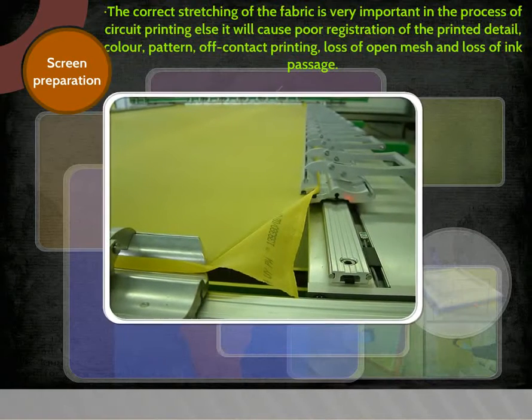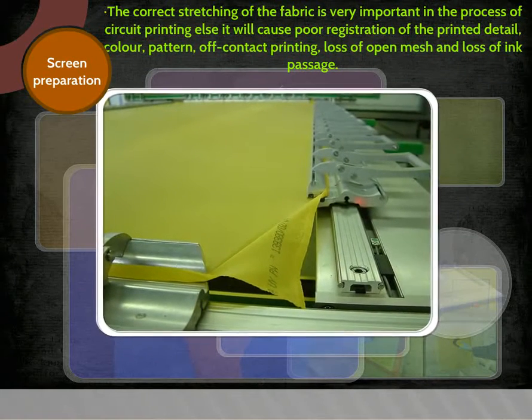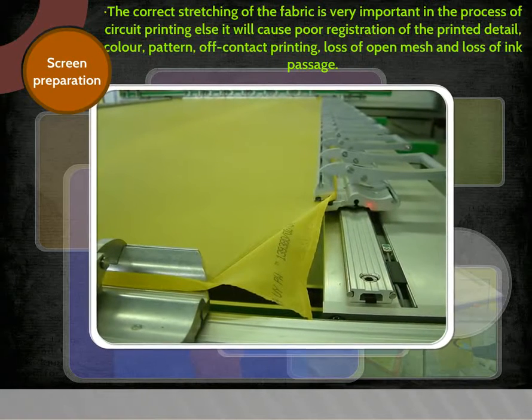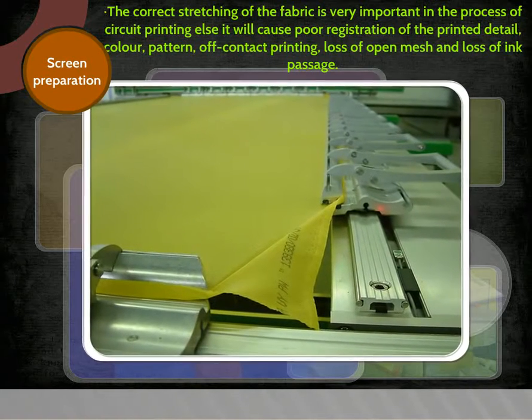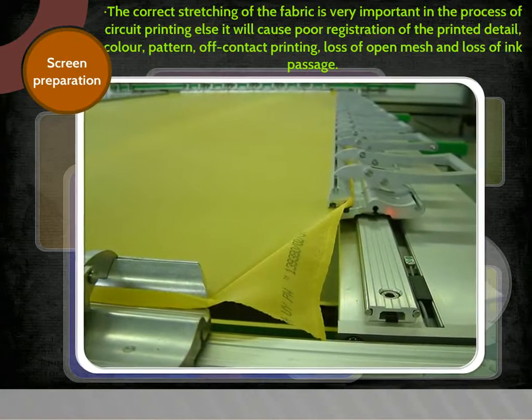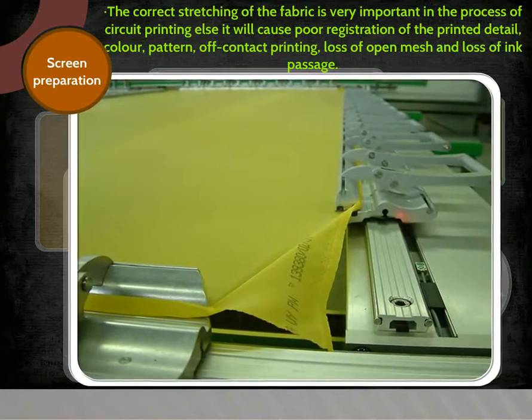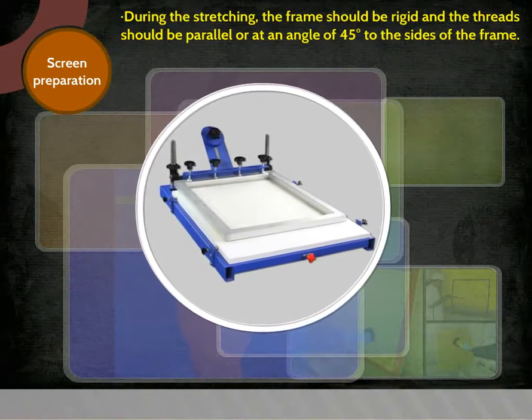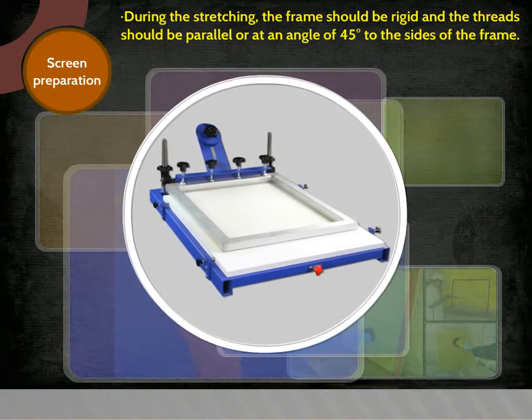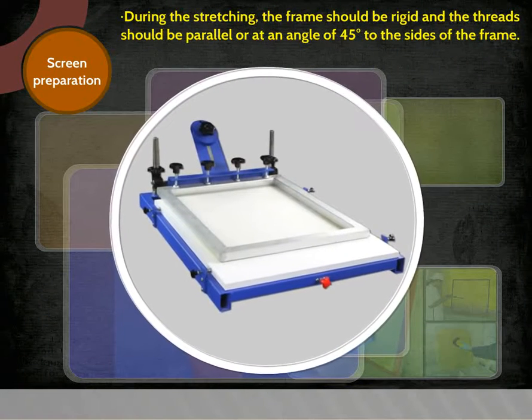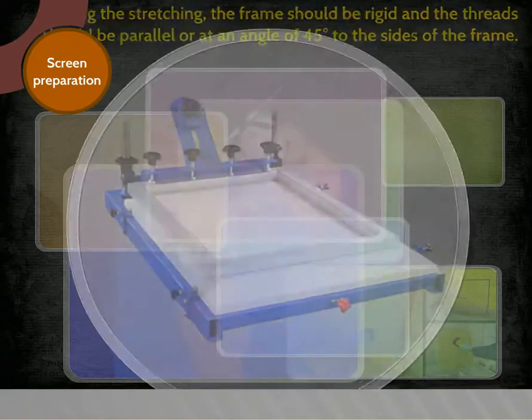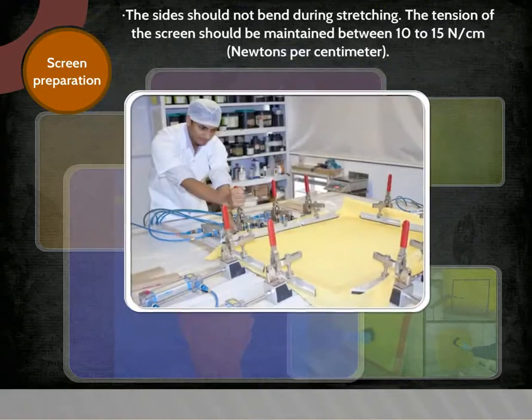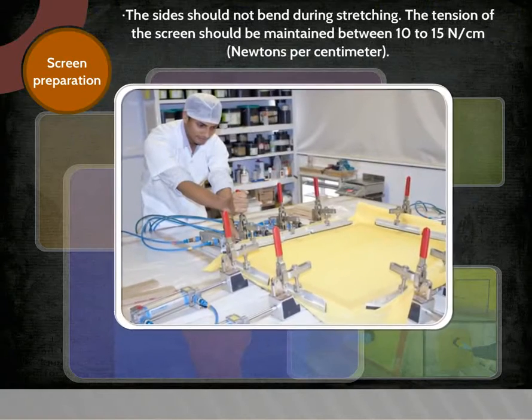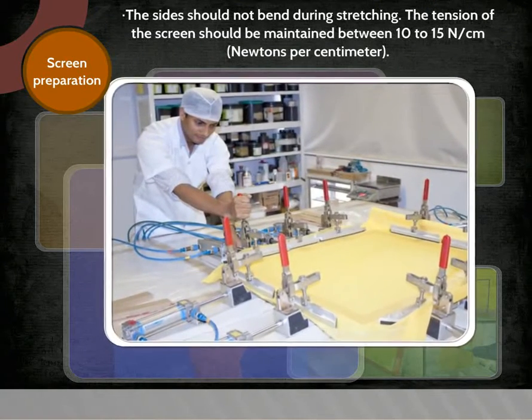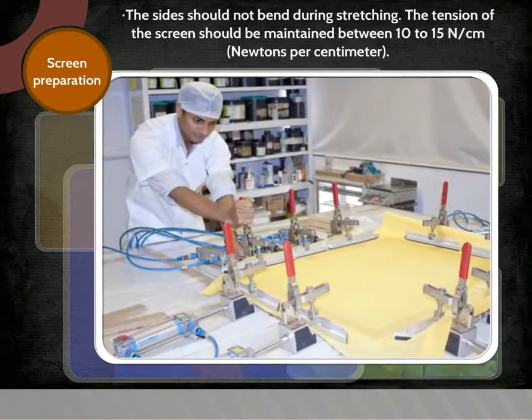The correct stretching of the fabric is very important in the process of circuit printing, else it will cause poor registration of the printed detail, color pattern, off-contact printing, loss of open mesh, and loss of ink passage. During the stretching, the frame should be rigid and the threads should be parallel or at an angle of 45 degrees to the sides of the frame. The sides should not bend during stretching. The tension of the screen should be maintained between 10 to 15 Newton per centimeter.